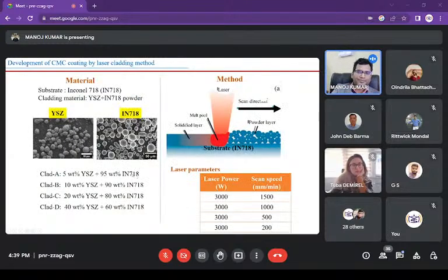So we took YSZ powder, which is yttria stabilized zirconia. Essentially, it is ZrO2, and then we also took Inconel 718 powder. We mixed them together in the proportion of 5 to 40% of YSZ, and we started depositing over the Inconel 718, and we tried to understand what happens with the process. So this is how the process looks. You take a substrate, you put the mixed powder over here, and then you pass a laser. This will melt and deposit over here.